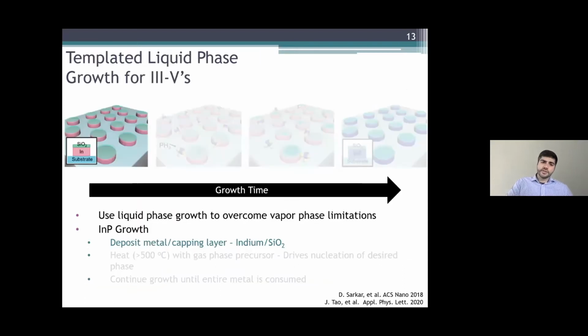And so the approach that we've taken for this is this templated liquid phase growth of III-Vs, where in this case I'm showing an example of indium phosphide. We take some substrate, so it's going to be silicon oxide, silicon nitride, titanium. We've done it with a whole bunch of different substrates. You deposit your group III metal, in this case indium, you cap it with a silicon dioxide cap, then you heat it up, and because it's capped with the silicon dioxide capping layer, even though the indium will turn to liquid at temperatures above about 160 degrees C, it stays in that original geometry.